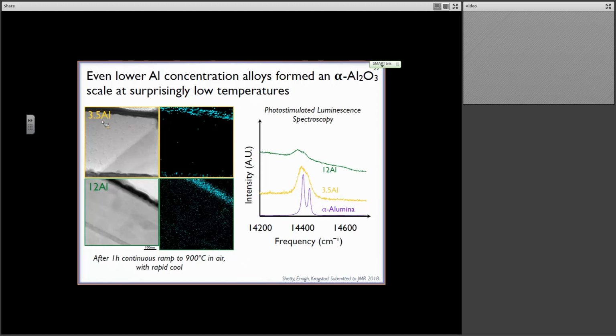Now, if we go to a lower aluminum concentration, for a coarse-grained alloy we would expect this to form a chromia scale. But because we have a nanograin structure to start with, the lower aluminum concentration is sufficient, again, to make an aluminum oxide. Many of you familiar with oxidation behavior know that alumina comes in many forms. It can be amorphous, it can have a wide range of polymorphs, not all of which are equal. But the interesting thing about this low aluminum containing oxide scale is not only is it aluminum oxide, it is the desired equilibrium alpha phase.